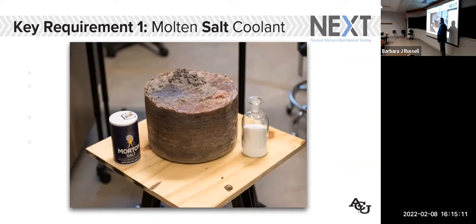It turns out when you get it up to 850 degrees or something like that, it melts and it's warm enough that it starts glowing red. It doesn't look nice and white anymore. But if you just melt it in a pot and then allow it to come back down to room temperature, it doesn't look white anymore. This is a lot of steel rusted inside of that salt because in the atmosphere, it corrodes pretty quick. So that's our pillar of salt that we have in our lab to demonstrate what salt looks like when you melt it in a pot and bring it back to room temperature.